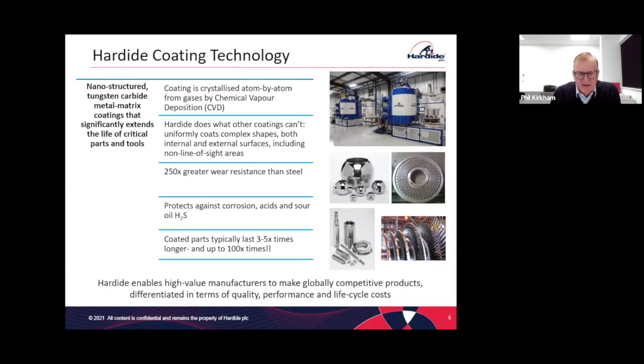As I mentioned previously, it does things that other coatings can't, particularly uniformly coating very complex shapes and inside and outside of surfaces. You can see there in the middle on the right there's a disc with hundreds of holes in. It's a plastic extrusion die where plastic is extruded through those holes and cut off into small pellets. We coat inside the holes in that component, which is something other coatings couldn't do. Next to that, there are ball valves, spherical ball valves. Below that, some pump components, and on the bottom right there are steam turbine blades.